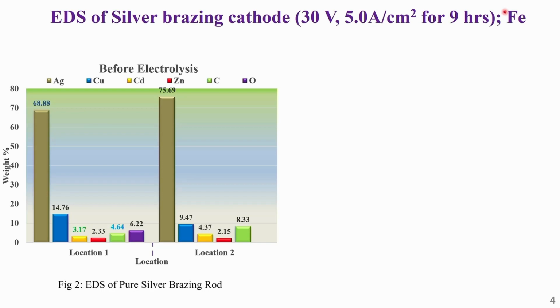This slide shows the EDS analysis of silver brazing cathodes. Electrolysis of 1 molar aqueous potassium carbonate is run at 30 volt with 5 ampere per centimeter square current density for 9 hours. Figure 2 presents the elemental composition of silver brazing before electrolysis, and its EDS analysis shows that it consists of silver, copper, cadmium and zinc.